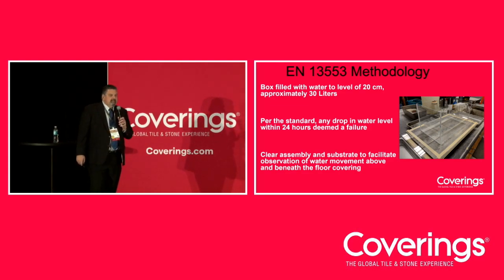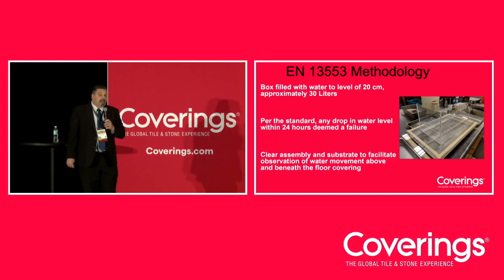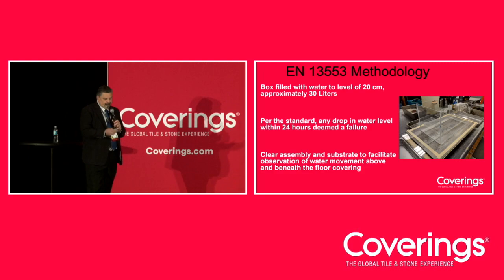There is a test in the European Union. There isn't one here in the US, but in the European Union, there is a test for testing how waterproof a vinyl flooring assembly is. Basically, you take a box with no bottom in it, you silicone it to the surface, and then you fill it up with 10, 12 inches of water, 20 centimeters of water, which equals about 30 liters of water when you get it all in there, and you see what happens. If it loses any water over the course of a day, it's not waterproof.